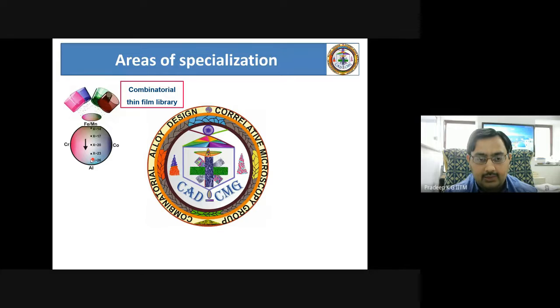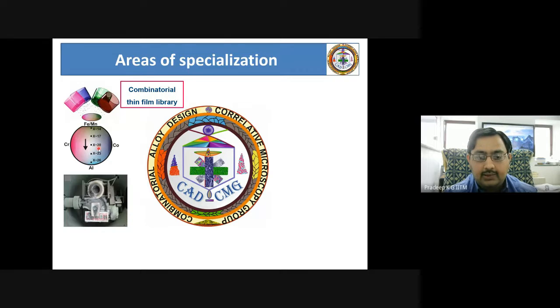That means from the thin film library, we get a wide range of compositions identified and their phase formation studied with little materials expenditure. And the identified composition or the range of composition, we can then carry forward to produce in the bulk form. So this is a picture of the induction melting furnace, where you can get a master alloy of the fixed composition identified from this combinatorial thin film.